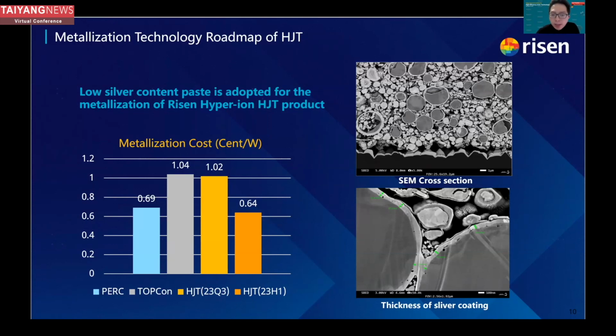We think the shell has around 80 to 100 nanometer thickness, and with this we reduce the silver consumption a lot, because basically only 50% of the silver is used. We reduced from 100% silver content to about 50% for now, and thus we have reduced the metallization cost to about 1.02 cents per watt, basically the same level as TOPCon. And we believe that with further study and R&D, we will reduce our silver consumption to 0.64 by next year, reaching the same scale as PERC.